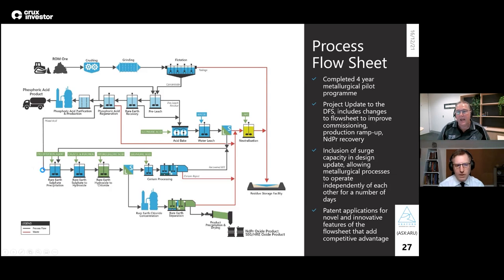And about 20% excess sulfuric acid, and that goes back in to regenerate our phosphoric acid in the pre-leach. So all of the excess acid we add into the bake ends up leaching apatite and making phosphoric acid byproduct. So that's why our operating costs can be so low. So the apatite provides you with both the rare earths and the phosphorus. And the phosphorus goes to one product and the rare earths go elsewhere.